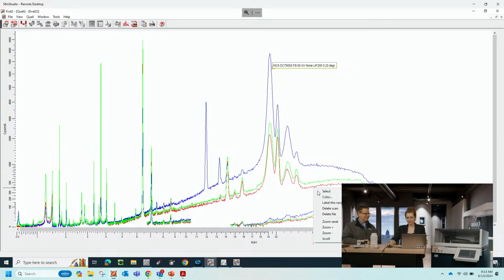And then what I have here, the red one, that's my powder. Sorry, I wanted to rename it. The red one is the powder. It says LP, loose powder. And then the green one, because I like it best, and green is gold, that's the pressed pellet. So one thing we see is this blue one has one peak that the others don't have. That's bromide, because I used lithium bromide as a wetting agent. That's important to get the fusion disk out of the mold. But other than that, all of the peaks are at the same position. What you can also see is that the green one is always the highest. So if I look for traces, pressing a pellet, compacting it with a high amount of sample, really gives us the best intensity.